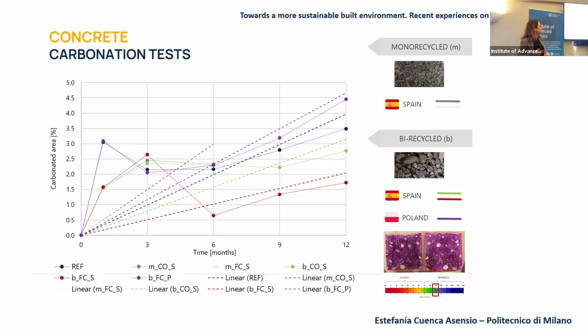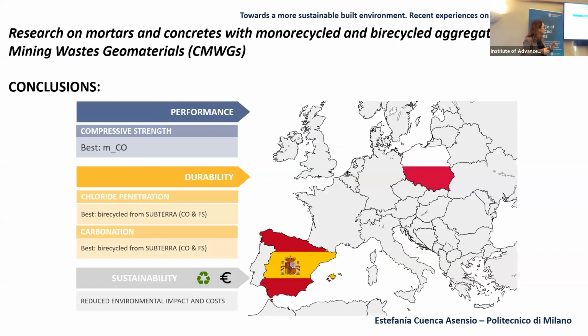What's quite good is that the experience was satisfying, because it's possible to use a double recycled concrete with properties that are really interesting in terms of chlorides, compressive strength, mechanical behavior, and so on. And it's possible to produce this material using waste, which otherwise is a huge problem, because it's hard to manage this kind of waste. So this is our second experience.